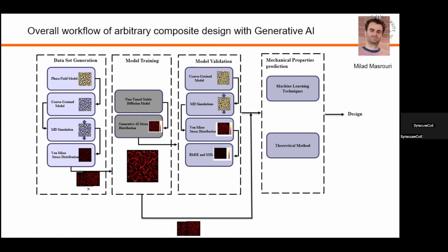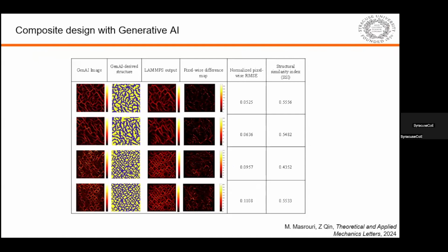And then the generative AI just learned the stress distribution and directly predicts the material composition together with the stress distribution. So once we have these models, we don't need to get some design and then do the simulation to predict the stress field and then select which design can be better. But generative AI generates all the possible conformations and the stress distribution at once. So here are just some examples. These images are fully synthetic from generative AI. Then we can take the conformation of the material distribution and run the MD simulation and get the actual stress distribution and then compare the difference. So pixel by pixel, there's still some difference, but that difference is very small.